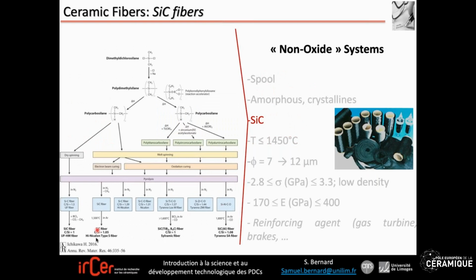Here is a map by Professor Ishikawa published in 2016. He reviewed the different types of silicon carbide-based fibers, and you can see the different silicon carbide fibers that are industrially produced. The cost of these fibers is quite expensive, from $1,500 per kilogram, I would say, for the lowest purity fibers, to more than $10,000 per kilogram for the highly pure silicon carbide fibers.